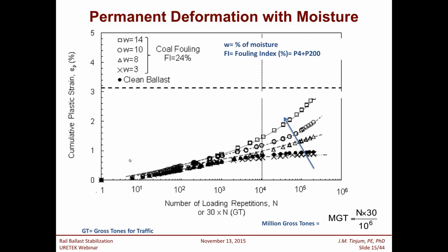And you see as we increase the retained moisture going from 3% to 14%, you also get that exponential increase in cumulative plastic strain as moisture is added to the system. So in summary, damage to the rail system comes from many varieties. Number one is the loads themselves, and heavy axle loads will increase the damage more than lesser loaded cars. Two, the higher the fouling index, the higher the plastic strain. And three, the higher the retained moisture, the higher the permanent deformation of the ballast system.